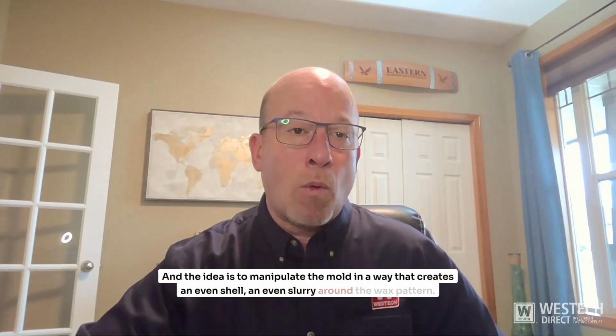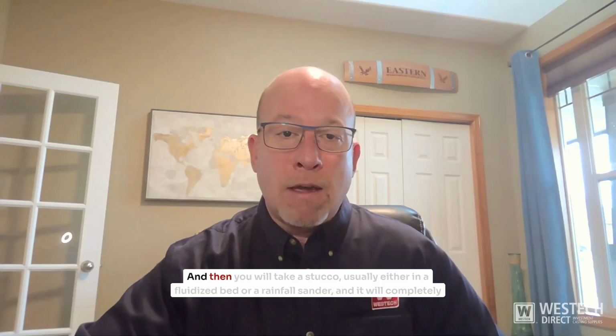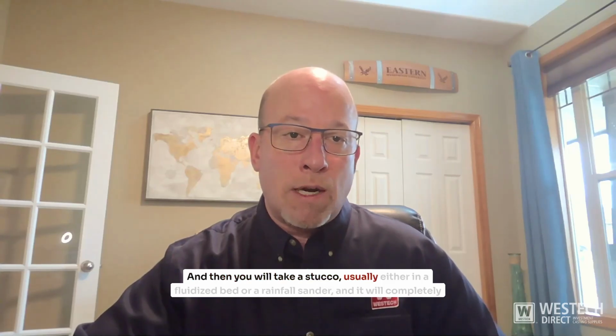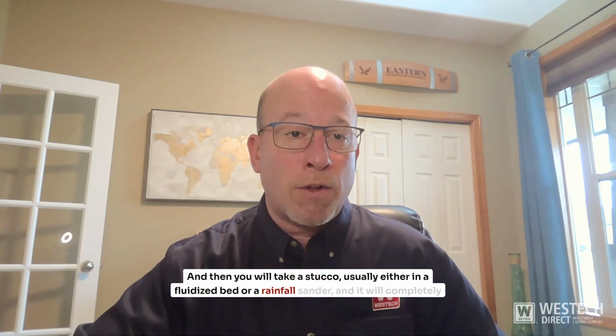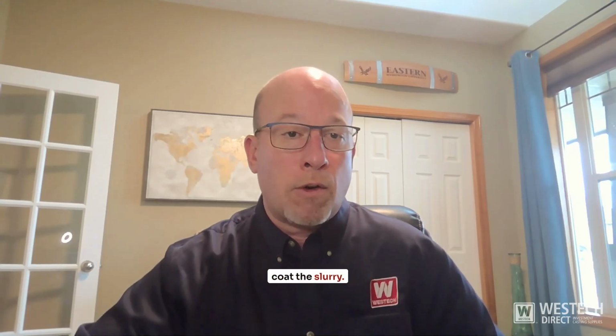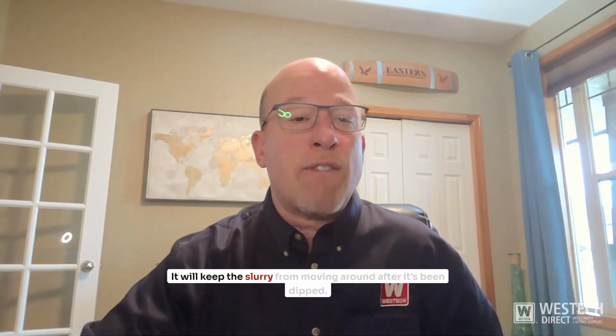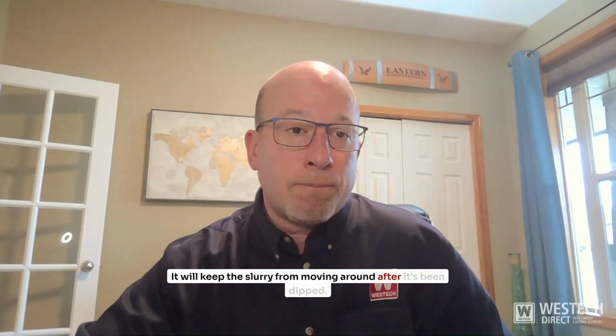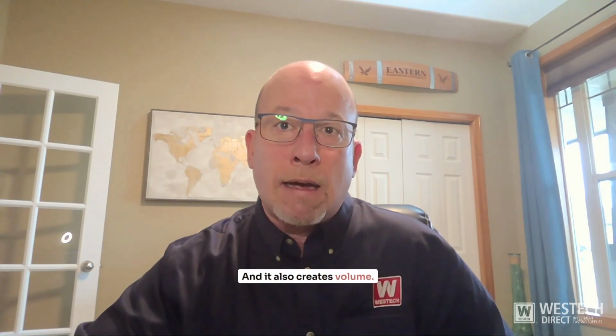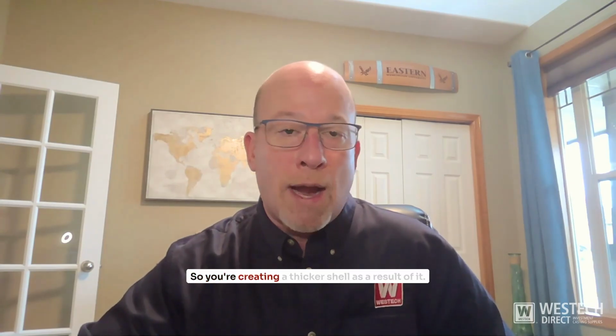An even slurry around the wax pattern. And then you will take a stucco, usually either in a fluidized bed or a rainfall sander, and it will completely coat the slurry. It will keep the slurry from moving around after it's been dipped, and it also creates volume. So you're creating a thicker shell as a result of it. And then so on and so forth.